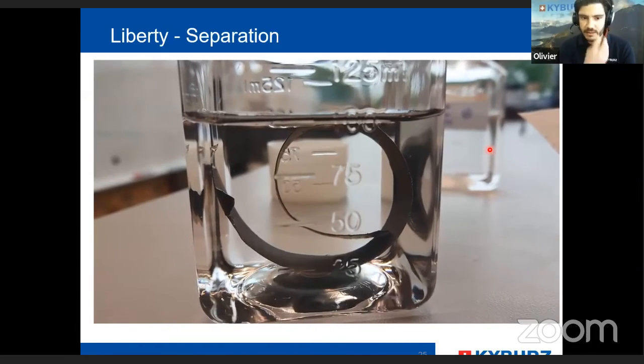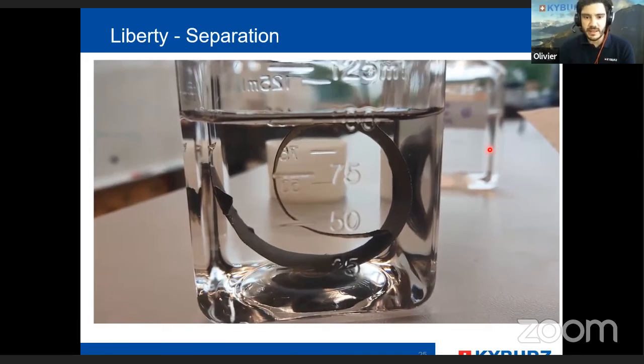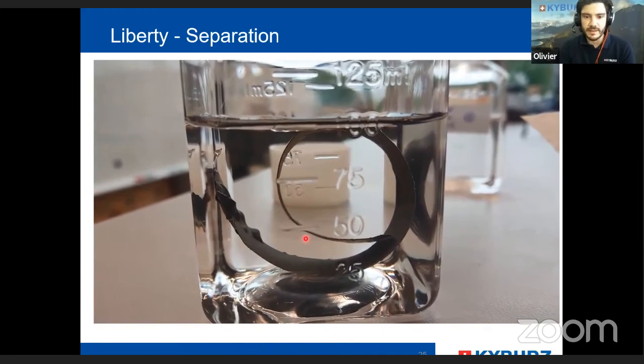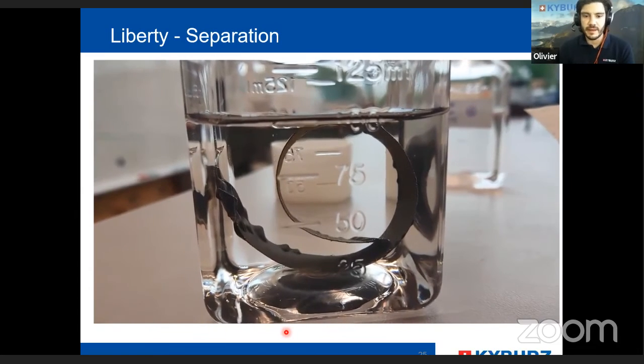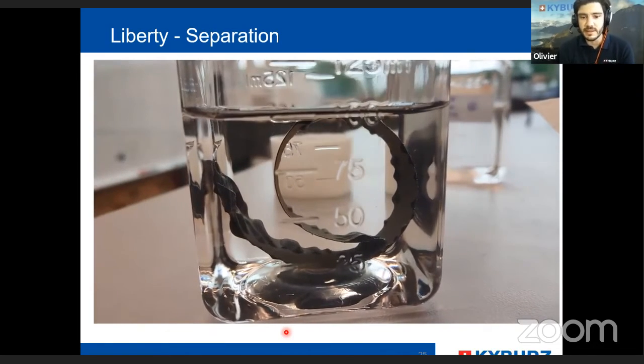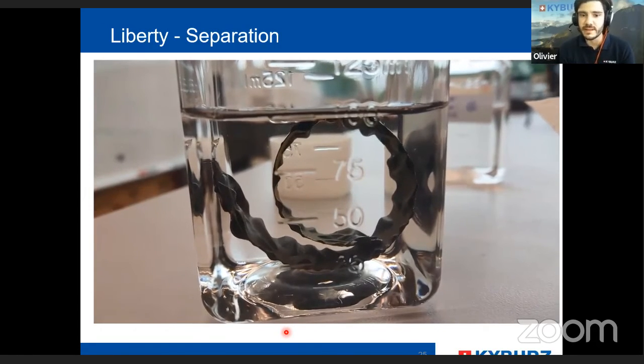Because we didn't destroy the cells before, and in the first step of the production of a cell, the coating paste, they use, in our case, a binder that is water-based. So now we can put the electrode inside the water, and without energy, the active material gets separated from the aluminum foil or from the copper foil. And here a little movie. So this is water and the cathode, and you can see here, without energy consumption, the active material gets separated from the aluminum foil. This is real time, and the cathode was 20 seconds inside the water.